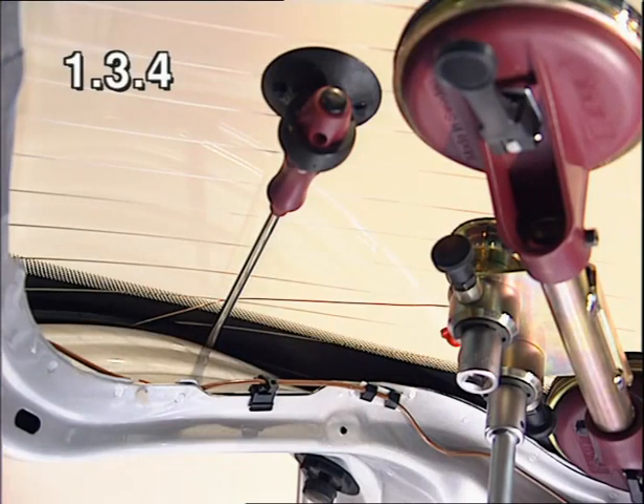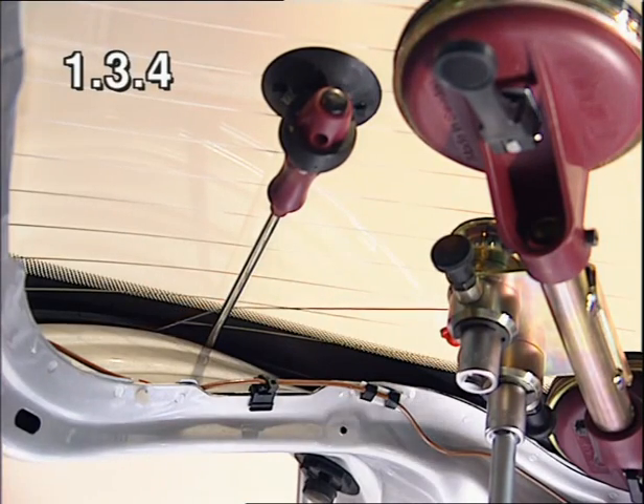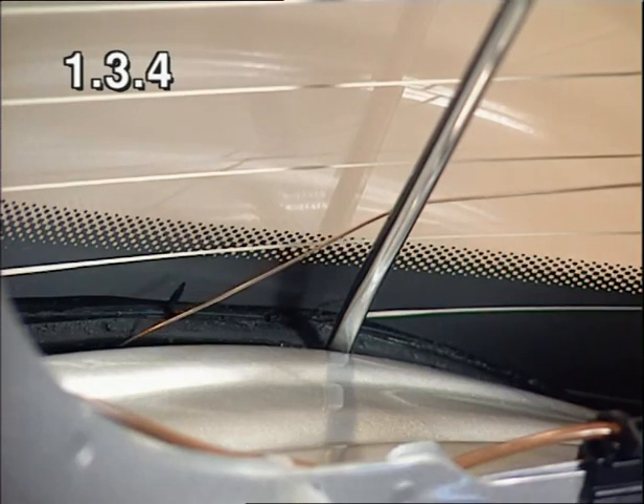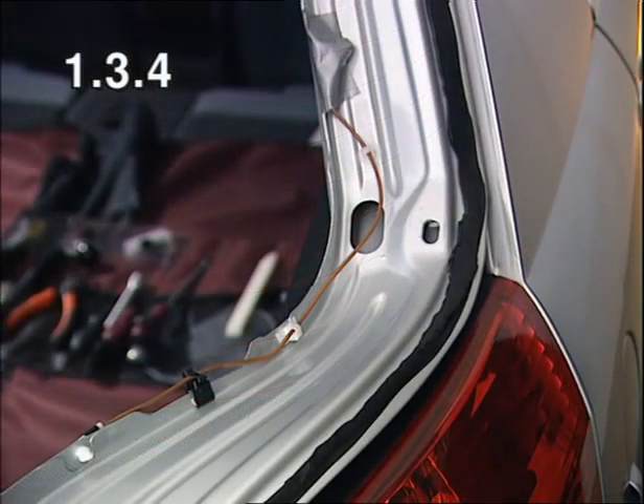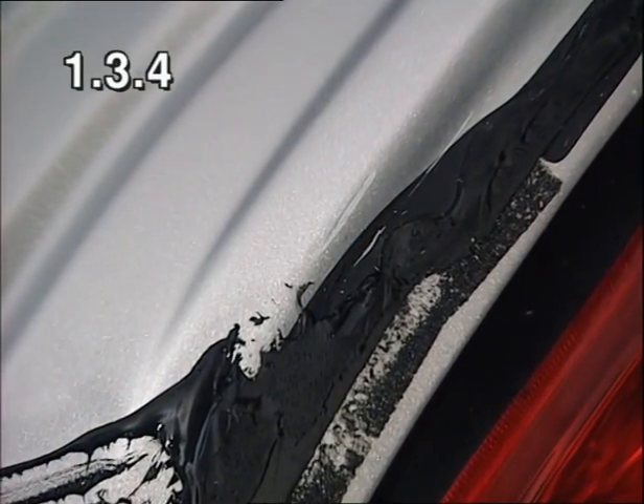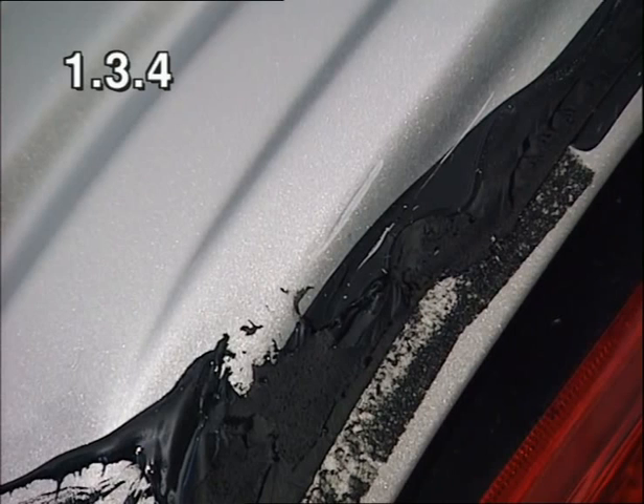On both sides, in the area of the high embossing in the frame, the wire is pressed against the window with the hole tool so that no damage is caused to the paintwork. If the wire is guided carefully and kept under observation, the worst thing might be a few relatively small scratches in the top coat, which however don't need to be repaired.